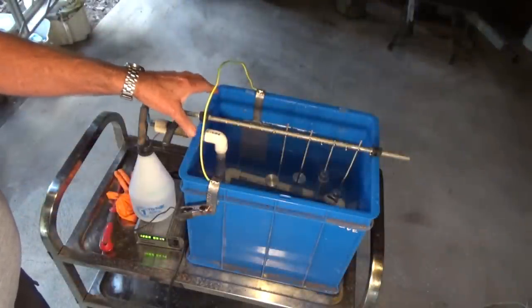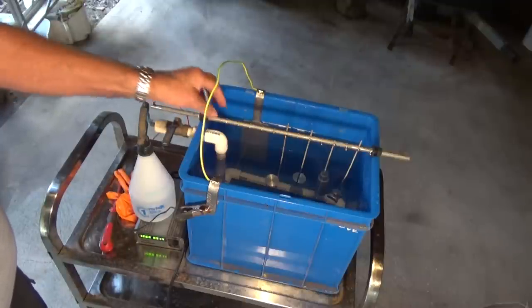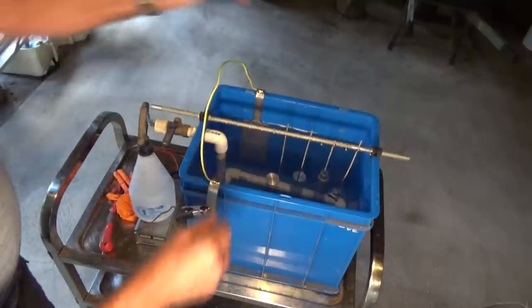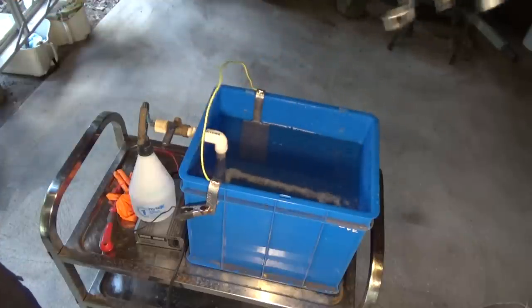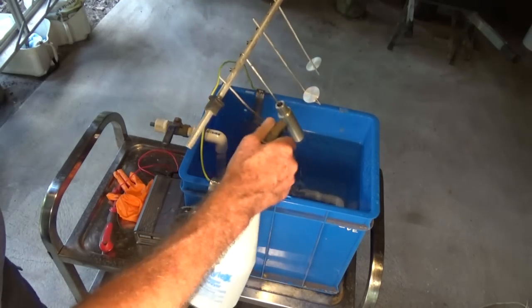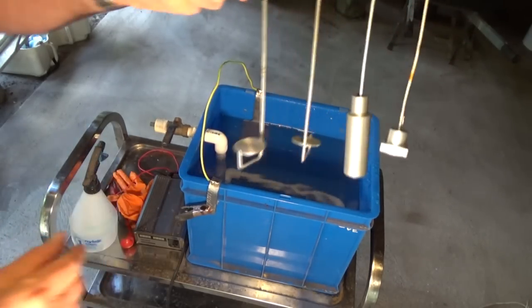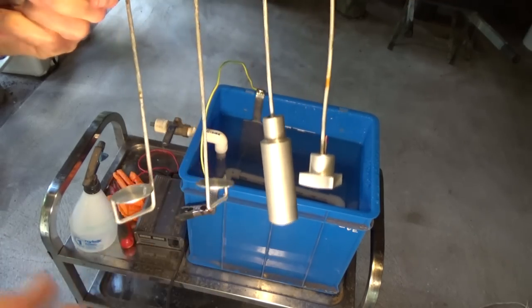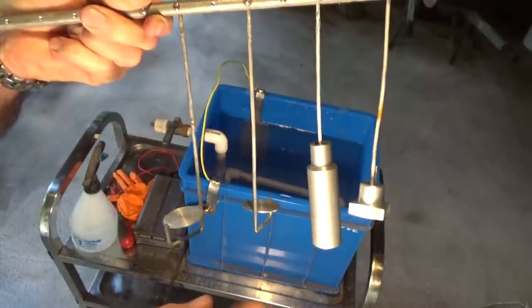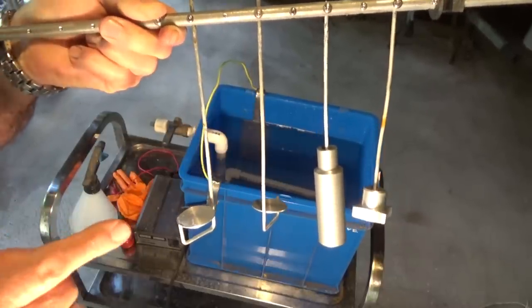Okay those parts have been in there now for about an hour and a half. From my experience 40 minutes is about the minimum. But if you want a good thick coating more than an hour, preferably an hour and a half. What we do now is just disconnect our power. These come out. What you want to do now is just give them a rinse. This is just demineralised water. The idea here is to stop any of that electrolyte getting carried over into the next process which is dyeing. If you've been successful what you should notice is that the surface of the part now has a slightly grey green look to it and it should be slightly dull like a satin finish. If it still looks shiny and like polished aluminium it probably hasn't worked and you need to look at your setup. But I reckon these are good. Let's get on to the next step which is the dye.